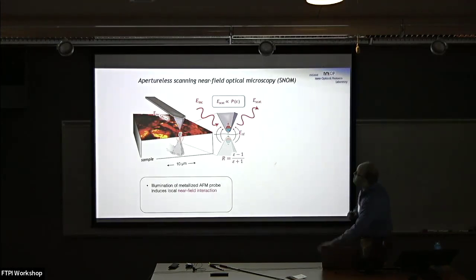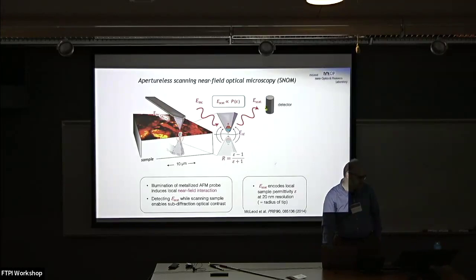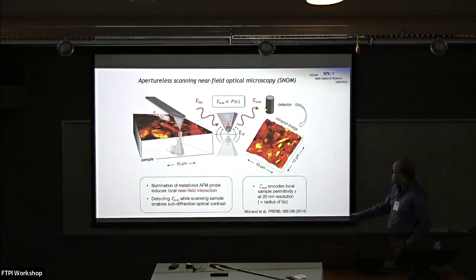So what do we do in the experiment? We collect the scattered light. Scattered light is proportional to the state of polarization of the probe. So we collect that scattered light in the detector, then we scan our probe around the surface. We measure that scattered light as a function of position. We get a map, okay, a map of the optical permittivity, a map of the optical conductivity.